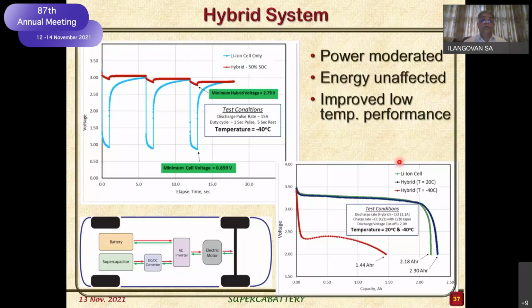But the problem is that, we have also tested with some pulse applications. The red one is with the supercapacitor being there, and the extent of drop is very much reduced. The blue one is only with the lithium ion cell, and the drop is so much. So that's how the battery plus supercapacitor combination is acting. So why is this issue coming up? If I have to drive a car, automatically the DC-DC converter will be there, then the battery will be there. If I have to operate the battery and supercapacitor together with a host of electronic equipment, then matching the voltages between these two different concepts becomes a little more difficult, and a lot of the hardware mass, the passive mass, is going up. So this is how the problem is setting in.